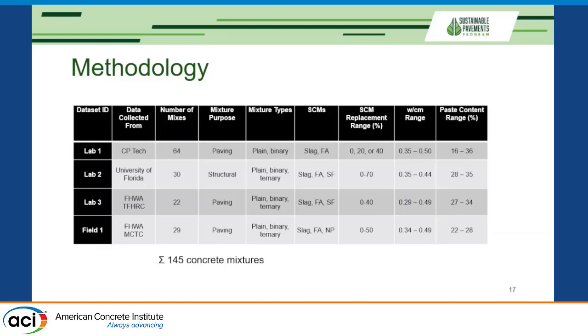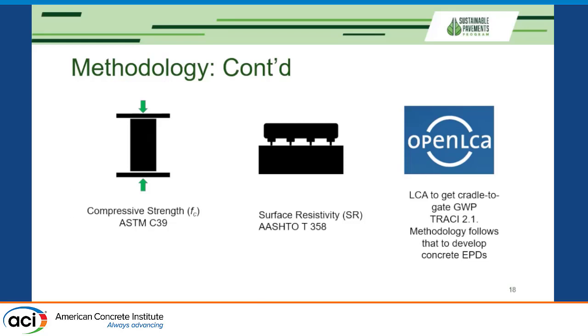And here you can see some other parameters. We are showing mix types. Many of them are paving. 3 of them, in fact, are paving. 1 is structural group of mixtures. We have different plain, binary, ternary mixes, different types of SCMs and their replacement ranges, water to cement ratios, paste content. So we are all across the board just to see what trends are holding up.